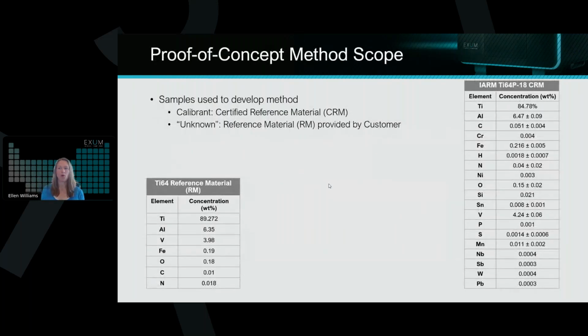So now to develop our own test methods for verifying the chemical composition of a powder, we first need a calibrant, a certified reference material. There are several of these available commercially, and so this one that you see on the right here is one that has been developed by a standards company, has gone through a rigorous testing process, includes uncertainty ranges for all of the elements, and we have a lot of confidence in the accuracy of these elements. So this is an excellent material to use as a calibrant, but then we also need a second material that can be used as a reference so that we can verify that the method that we're getting is giving us accurate results.